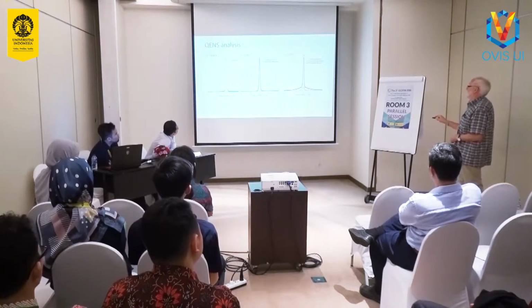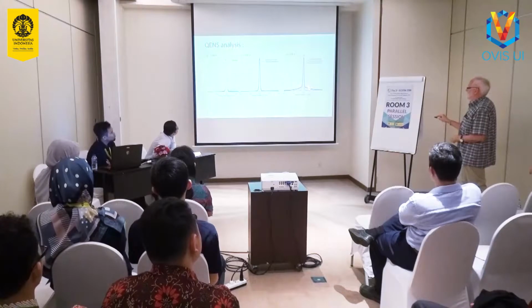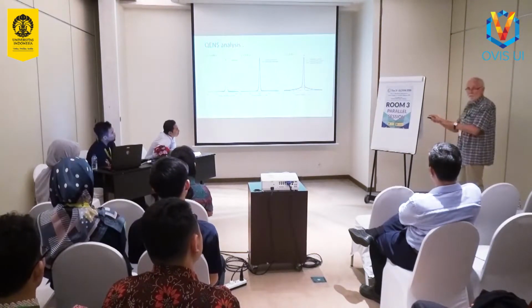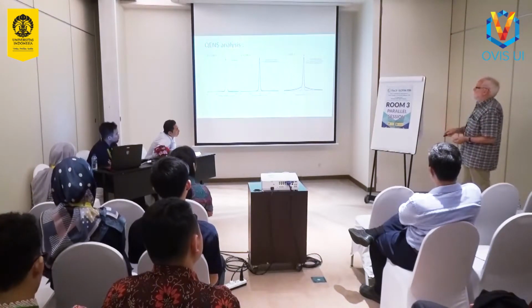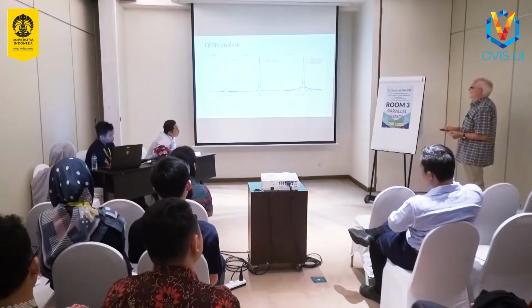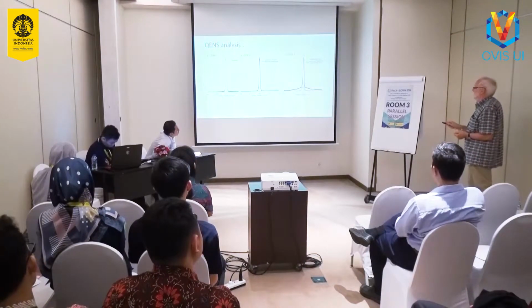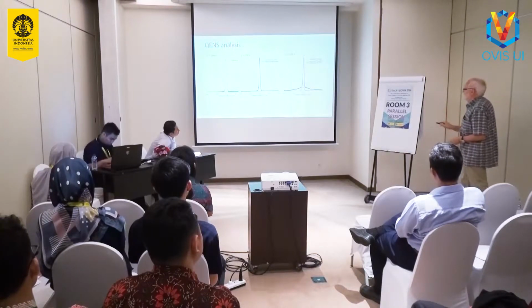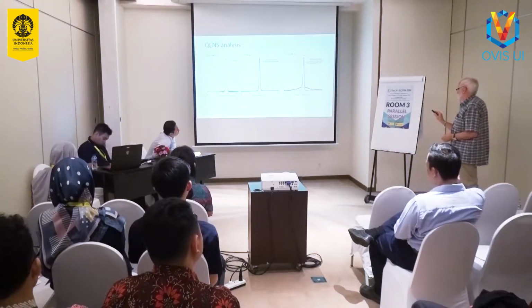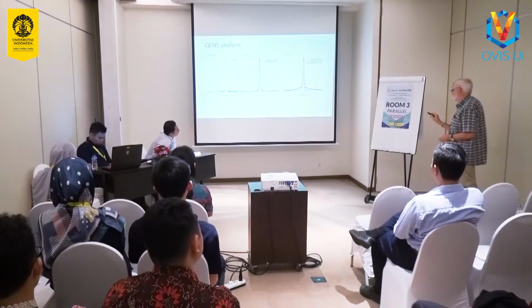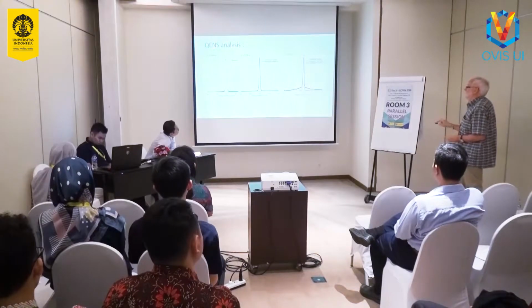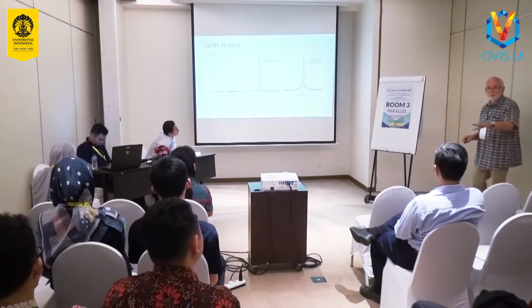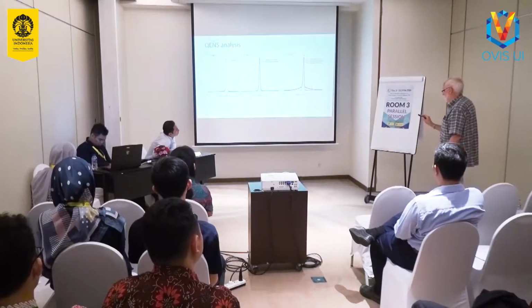And this is coming from the scattering of neutrons due to the motion of the molecule. The molecule is moving in the pores of the zeolite, and the neutrons are bouncing off it, being scattered with a very slight loss of energy, or slight gain in energy, depending on how they interact. And the result is a broadening of the elastic peak. This is what's called QENS. So it's the analysis of this that's going to give us information about the mobility, motion, the movement of the molecule in the pores.